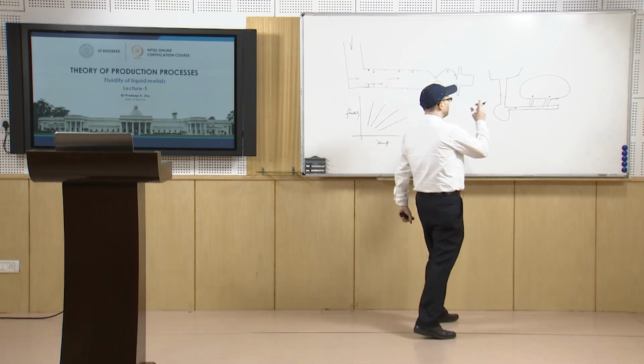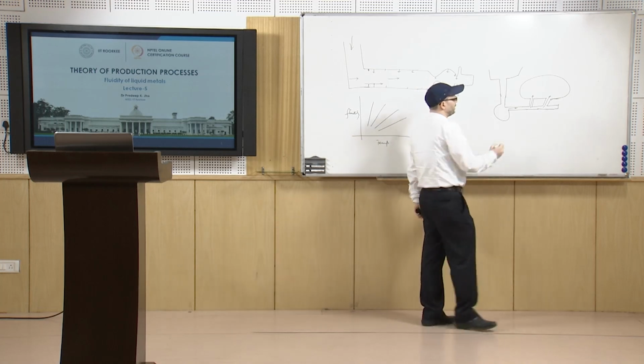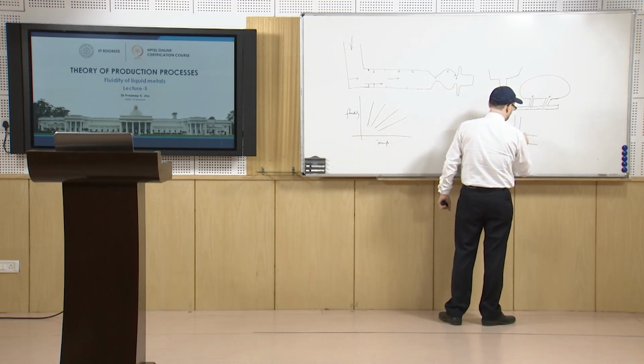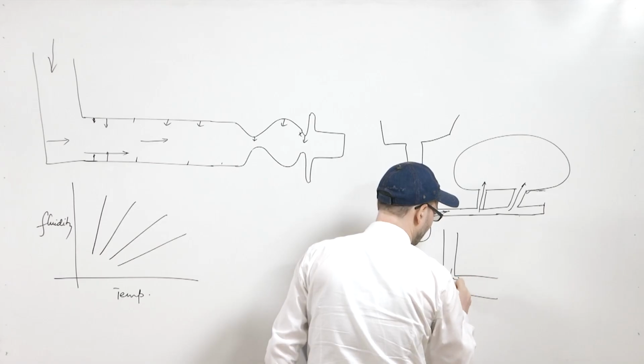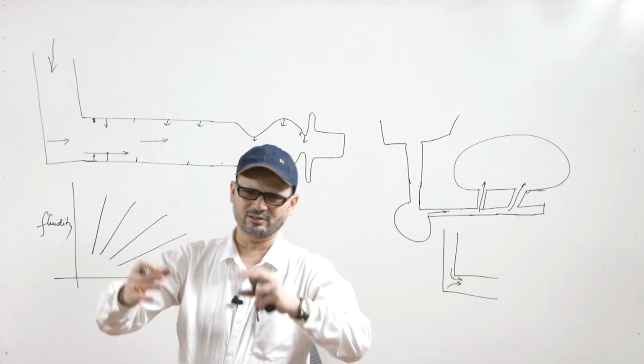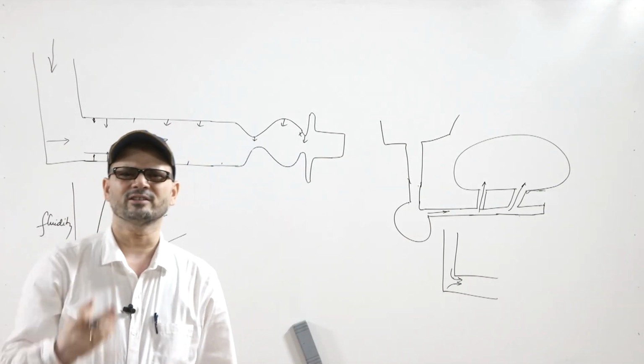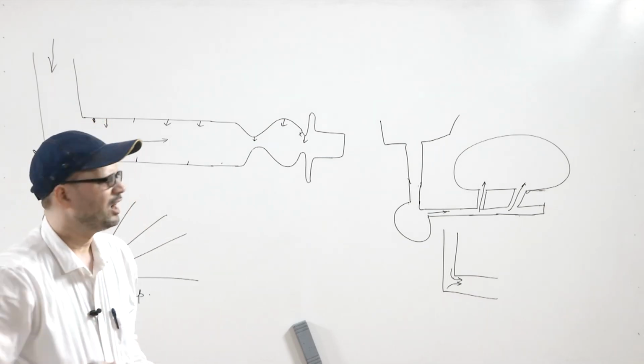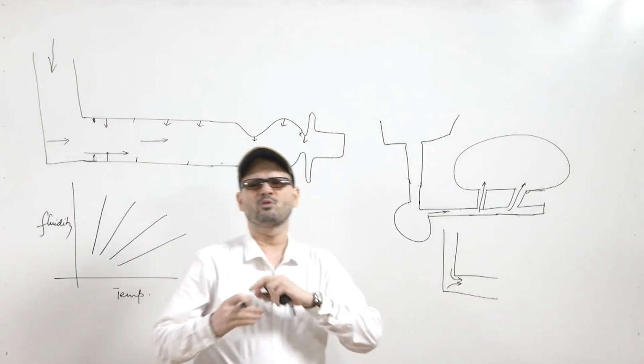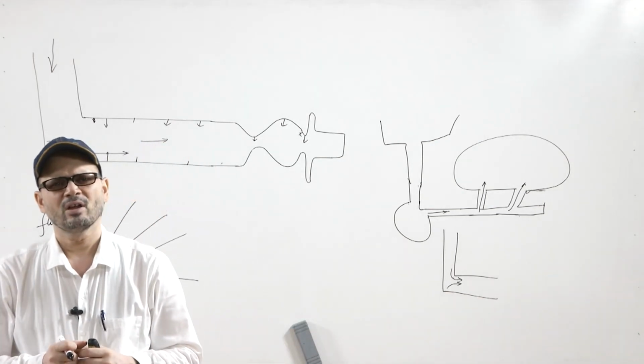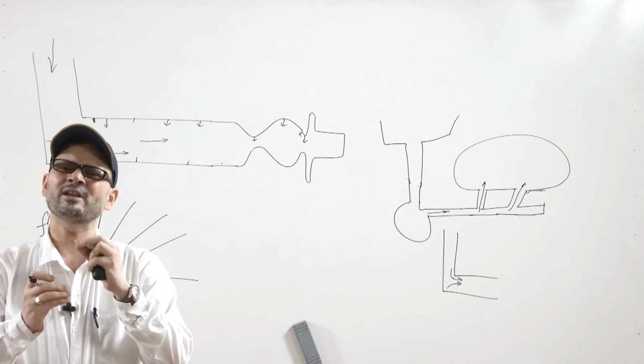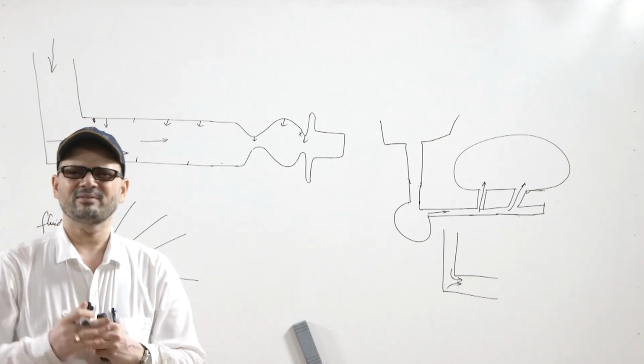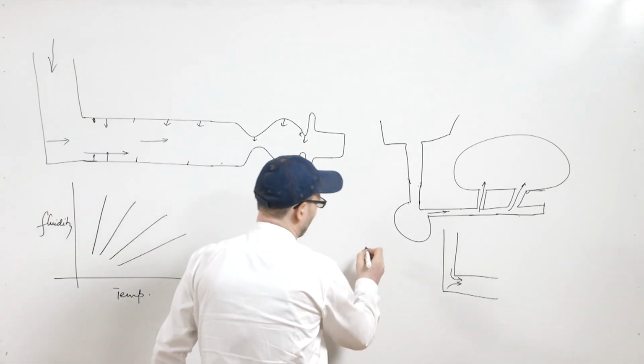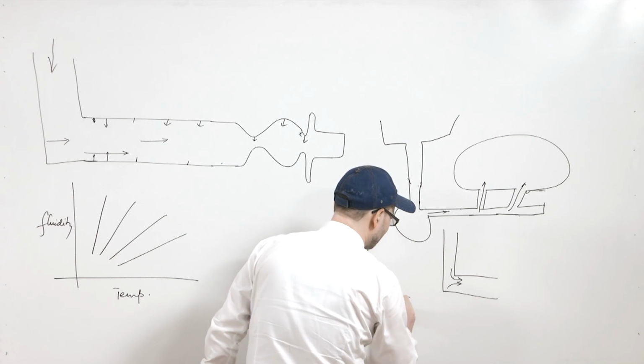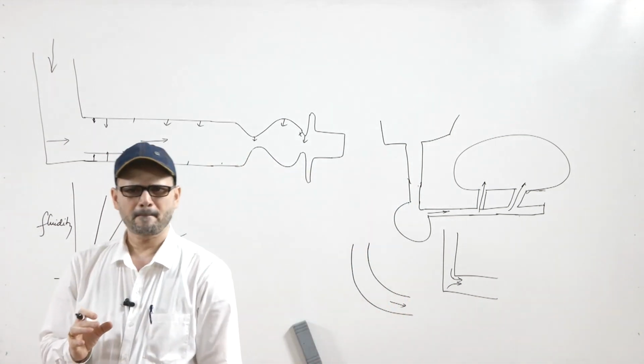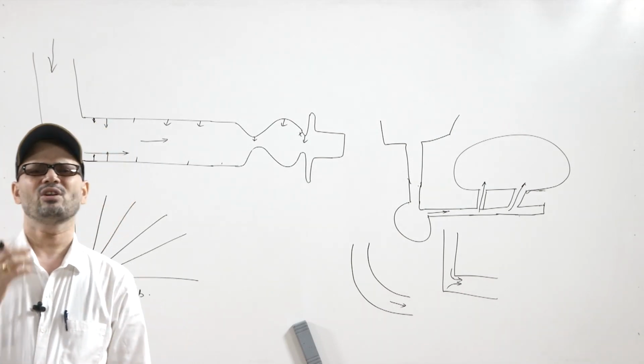You may see at many points you have abrupt section changes. Whenever you have abrupt section changes, you will have the formation of vena contracta, and the formation of zones where there will be adverse pressure gradient. At these places or at these bends, if you have more and more bends, you have energy losses. So, you should see that there is a minimum number of bends, or even if there is a bend, you should have streamlining. For that you should do these design changes.